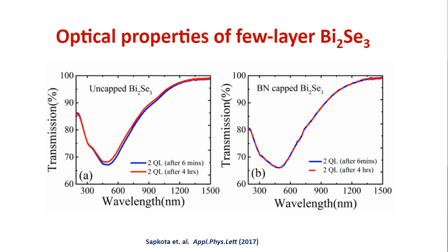The reason we did this was to protect the bismuth selenide layer from getting oxidized, because we are measuring the changes of a very thin film. If the film gets oxidized, we are not really talking about bismuth selenide anymore, right? So we have some other film. This was a genuine concern, so we did the test. What we found is the uncapped films do show some changes. So you can see the 2 data sets here.